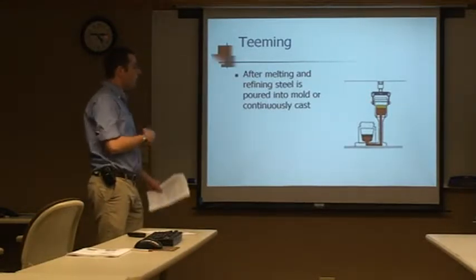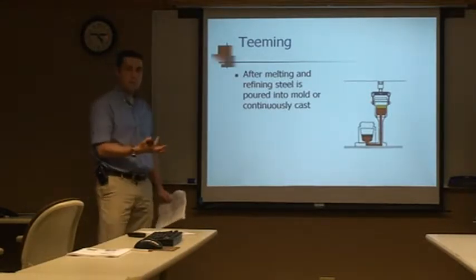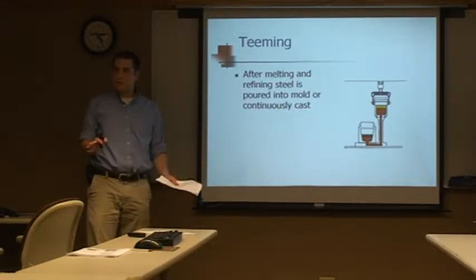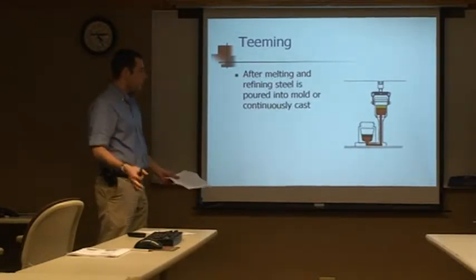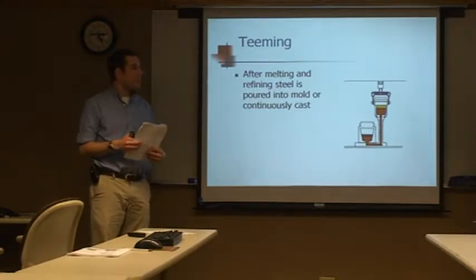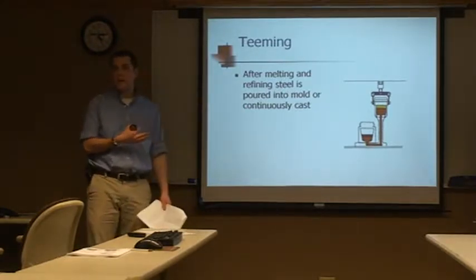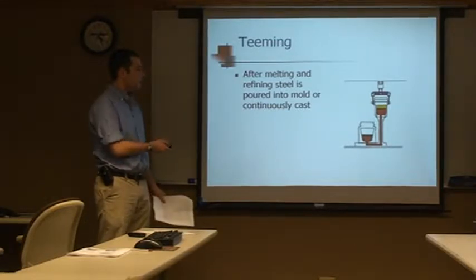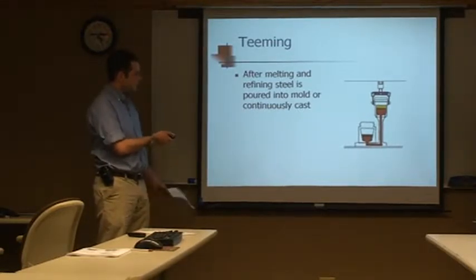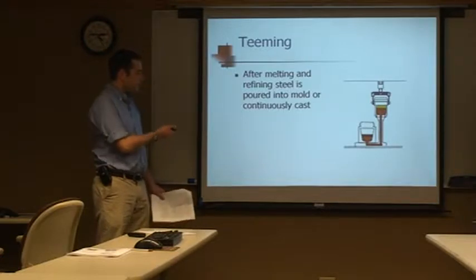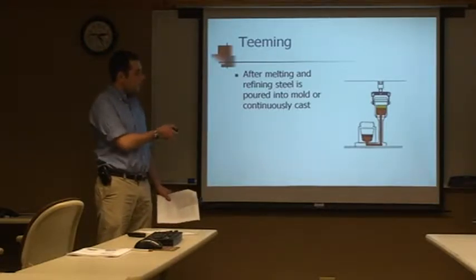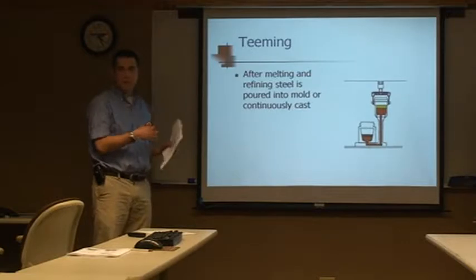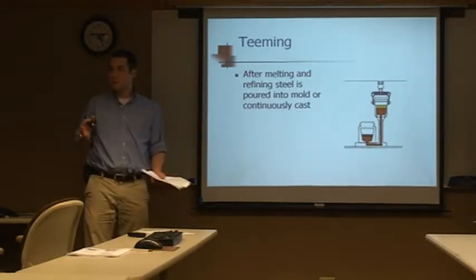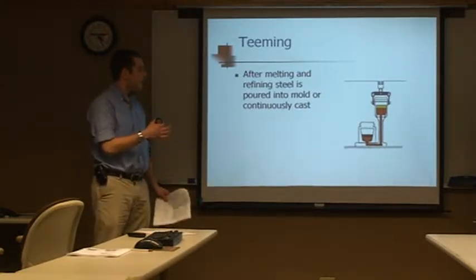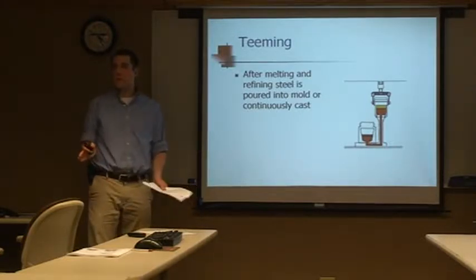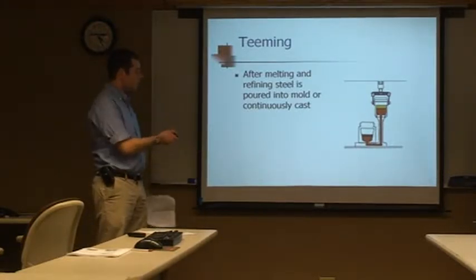The benefit of this technique is you get very smooth and even filling. You don't have very much turbulence when the molds are filling. That helps reduce the wear and tear on the teeming hardware, which is the ingot mold and also the trumpet. The trumpet and the runner bars are lined with ceramics that are one-time use. We run the steel through them once, and then we throw that material away. So that also helps protect the